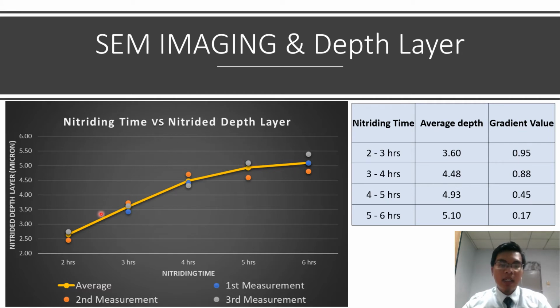This nitriding depth layer formation rate can be represented in terms of gradient value. As you can see here, 2 to 3 hours and 3 to 4 hours have the gradient values 0.95 and 0.88, which are almost similar, close values. However, for the 4 hour to 5 hour nitriding time, the gradient is 0.45, which is almost half of